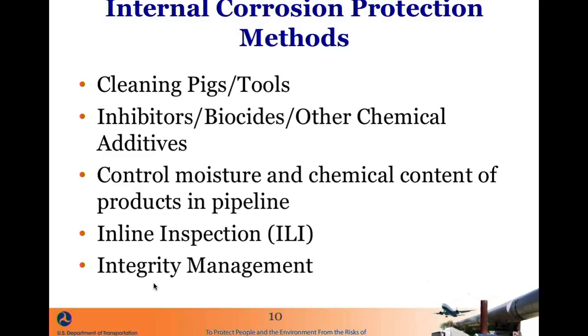Inhibitors are added to slow down corrosion rates, especially in liquid lines. Biocides are added to stop the microbes from growing. These are like antibiotics to keep the bacteria level down. And there could be other chemical additives as well. And inline inspection tools are one of the best tools to use to detect internal corrosion. And you'll see that throughout the pipeline safety regulations, running ILI tools is a part of effective integrity management to control corrosion rates.